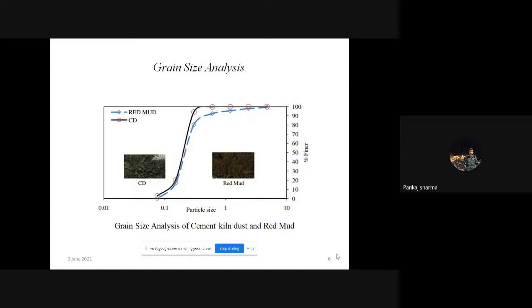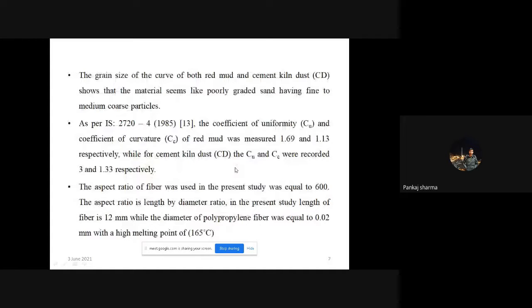Here is the grain size analysis for two different industrial wastes. That is, first is our CKD or cement kiln dust, and second is our red mud. From the curve, it seems like a poorly graded sand. This is not actually sand, but it seems like a sand, and having Cu and Cc values in the range of poorly graded sand. The aspect ratio of fiber is 600, having length of fiber 12 mm, where the diameter of polypropylene fiber is equal to 0.02 mm, having a high melting point.